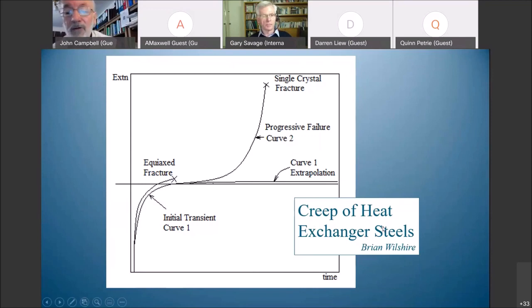Brian said, this is rubbish. There's only two parts. There's an initial transient and a final transient, and where they overlap appears to be the steady state. And what he did was to derive equations for the initial transient, an equation for the final transient, and this gave a fantastically improved way of predicting creep lives for certainly for steels, and maybe it's good for other things too. I wouldn't know.